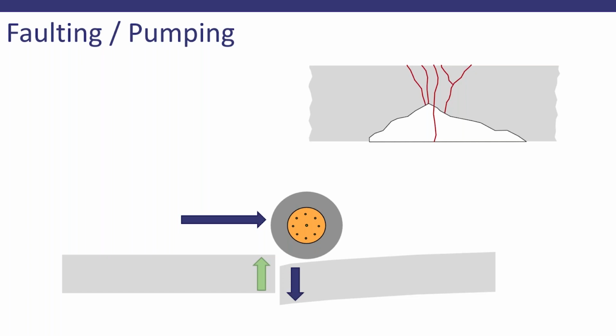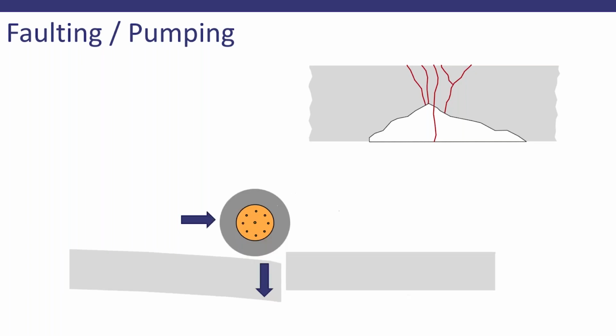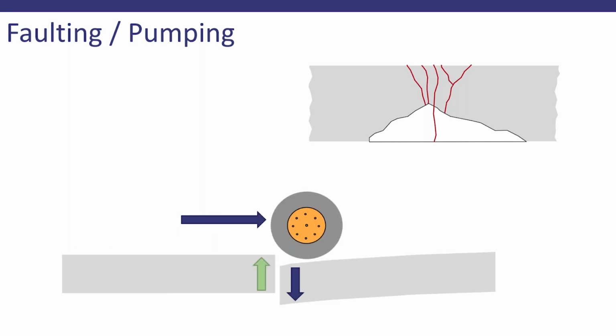So a lot of times when you're, say, going down the interstate and you're behind a big truck and they go across a wet spot and a lot of dirty water kind of shoots up out of that crack behind them. That's what's happening. They've hit that first slab, pressed it down, and then they've moved across the joint to the next slab, which has sucked some of that dirty material, some of that base material and subgrade, and then it just squirts right up behind them. So you can see that happening. That is a loss of material under the corners of those slabs.